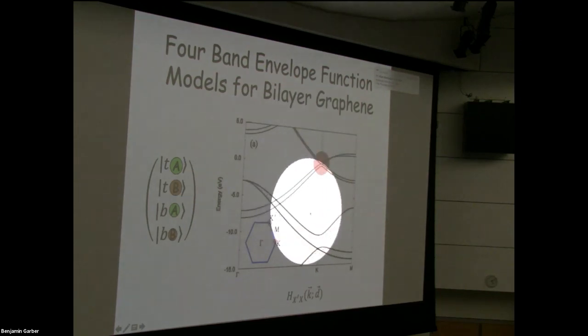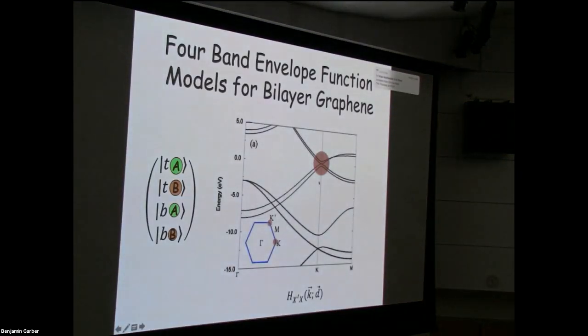I'm highlighting the low energy states, which occur at momentum near the Brillouin zone corner. When I showed you this for graphene previously, you may have noticed or known that there are two states because of the two sublattices of the honeycomb lattice. And so if you have two layers, then there actually are four states that are close together in energy. These states are split by tunneling between the two layers.